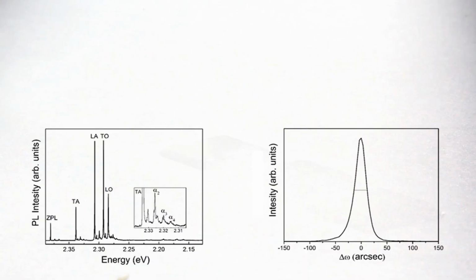And very nice, in the material which we were growing, we had very nice characteristic features. In the photoluminescence, there are some certain peaks which appear when the material quality is high, and the widths of them are narrow. So this is very good. And also in the XRD rocking curves, when we explored it, it had very narrow width of the rocking curve and so on. So this was a good indication of good quality material.